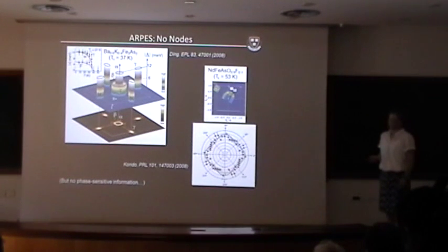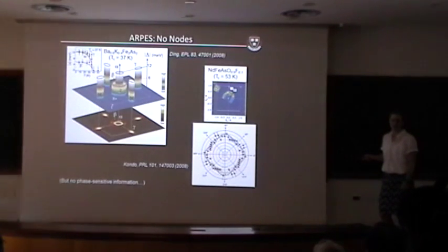Okay, so very early on, there were a couple of experiments. Actually, this was a quite heroic ARPES experiment. I think they glued crystals that were 100 microns or so on the needle of a pin. That was a beautiful photo. And they were the first to show via ARPES that the Fermi surface didn't seem to have nodes. And then there was a later experiment on the 122 materials, once larger crystals were available, mapping out in more detail multiple Fermi surfaces, none of which had nodes.